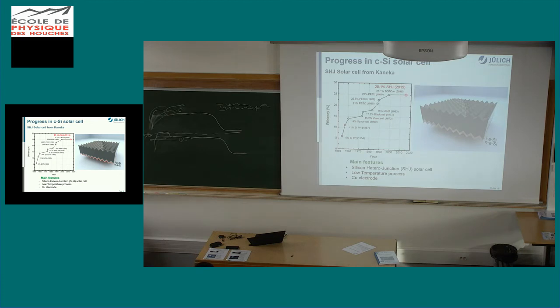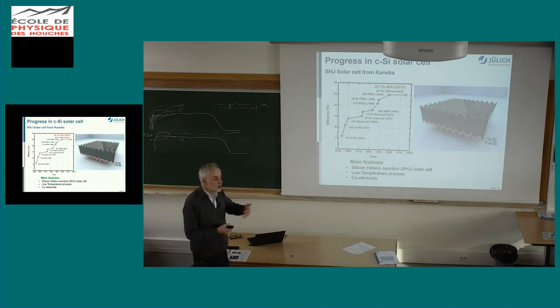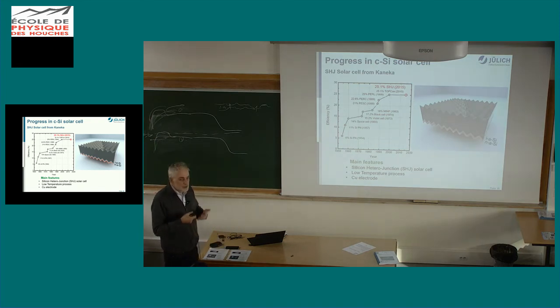Also here is a thin layer that has the purpose of enhancing the selectivity by passivating the minority carriers, so that nothing happens to the minority carriers, but still allowing the majority carriers, or the desired carriers, to get through. That is why you have this undoped amorphous silicon. From the amorphous silicon world, it's very well known that if you dope amorphous silicon, it has no photovoltaic quality. You only use doped amorphous silicon for the doping, for the contact. But if you want something that is photovoltaically active, just keep out the dopant atoms, keep out everything.